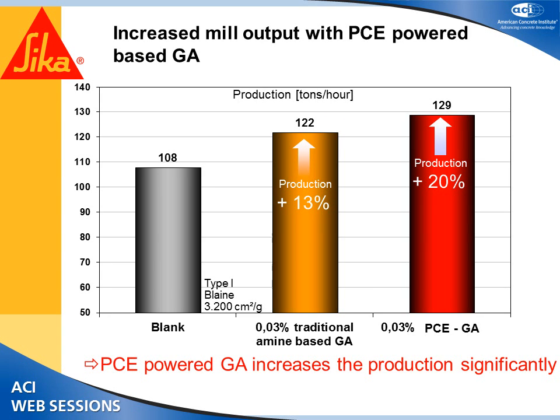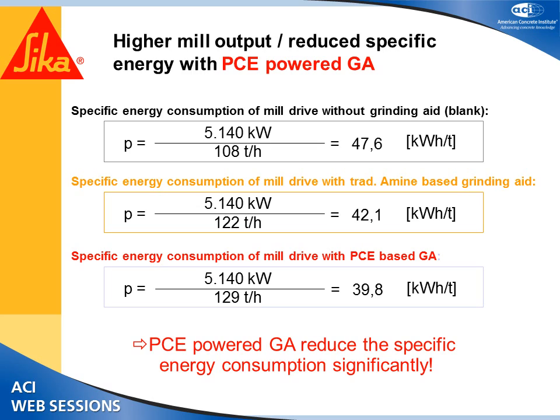And as you can see, this is from a cement plant trial. This is a blank without using any grinding aid. This was the production here. When you're using a traditional grinding aid, the production increased by 13%. When you used a PCE-based grinding aid, it was much higher than that. Same with the specific energy consumption. With the normal, it was 47.6. With traditional, it was 42.1. With the PCEs, it was lower.